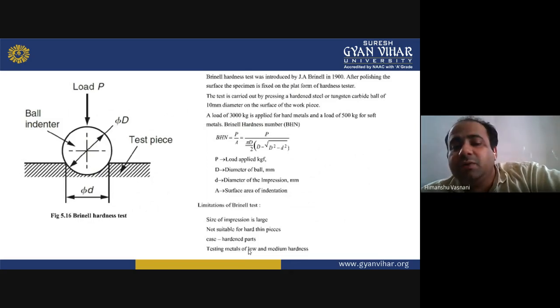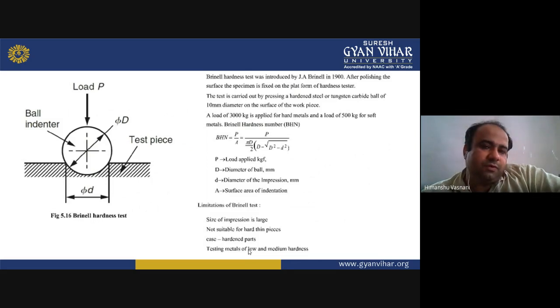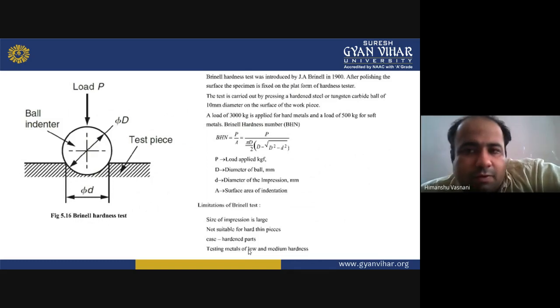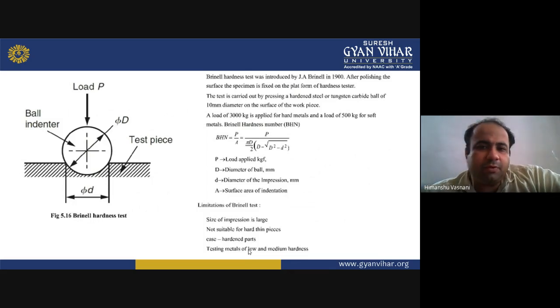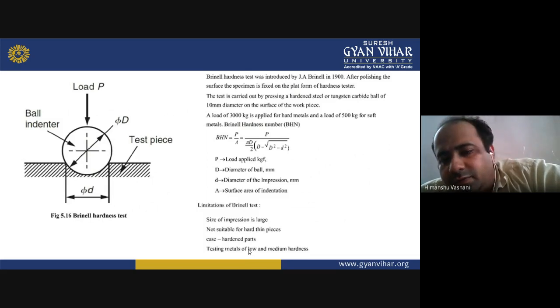The test is carried out by pressing a hardened steel or tungsten carbide ball of around 10 mm diameter on the surface of the workpiece. A load of around 3000 kg is used for hard metals and a load of around 500 kg for soft metals. BHN, the Brinell hardness number, is given by P upon A, where A is given by pi D upon 2 times, in brackets, D minus the root of D squared minus d squared. Here P is the load applied in kg.